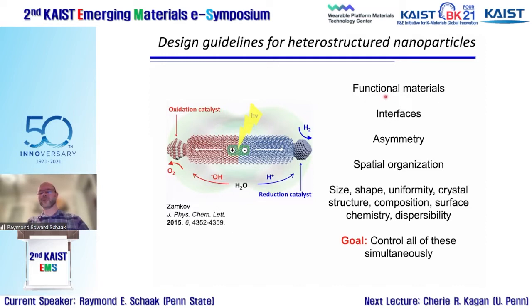And all that is on top of what we've been focusing on in the community for decades, right? That is controlling size, shape, uniformity, crystal structure, composition, surface chemistry, dispersibility, and all those factors that have been worked out for things like metal nanocrystals, quantum dots, et cetera, but now superimposed on all of these additional higher order features. As a synthetic chemist, I look at this in a general sense and the goal feels insurmountable, right? It's controlling all of those simultaneously, to really get the level of synthetic control that's needed for high yield, high efficiency nanoparticles like this.